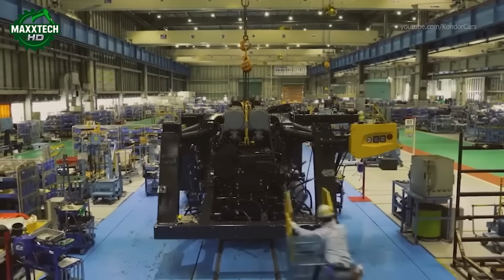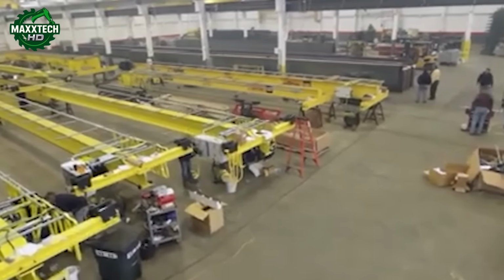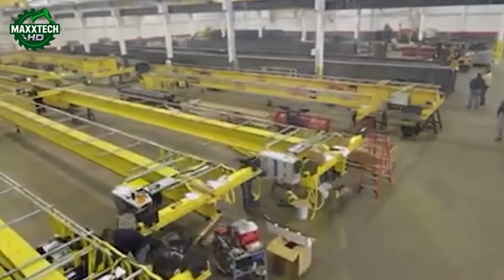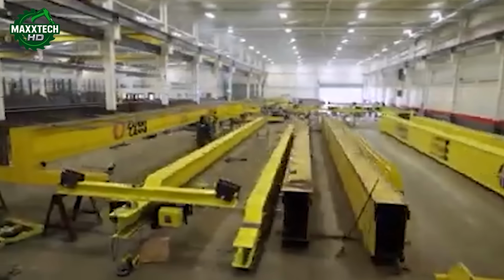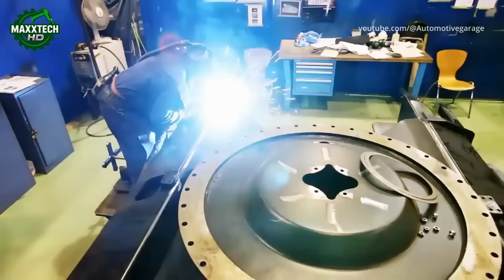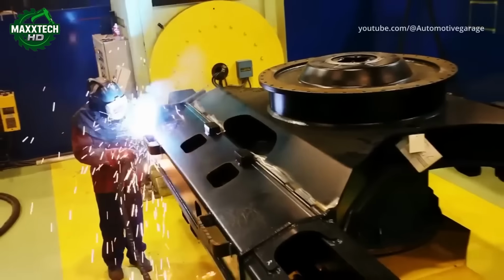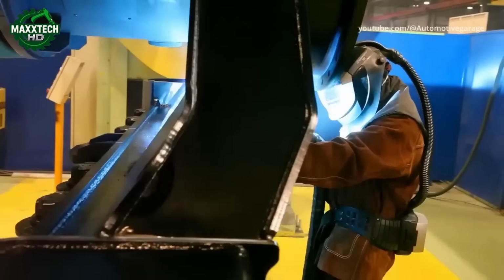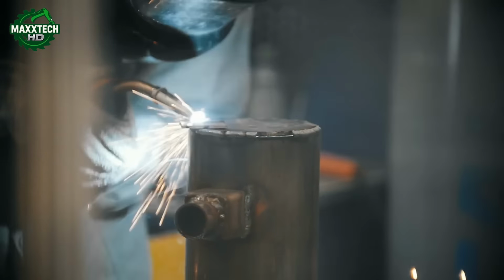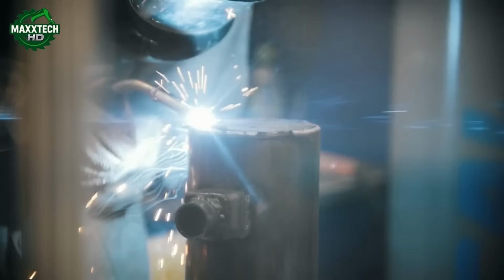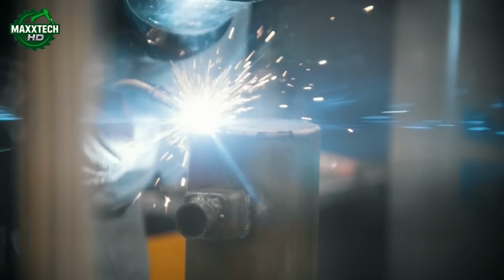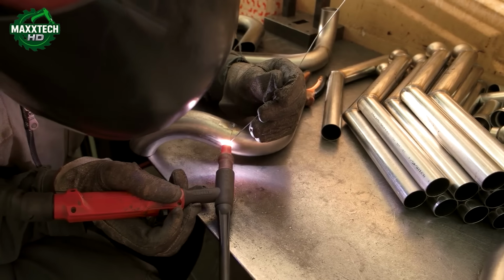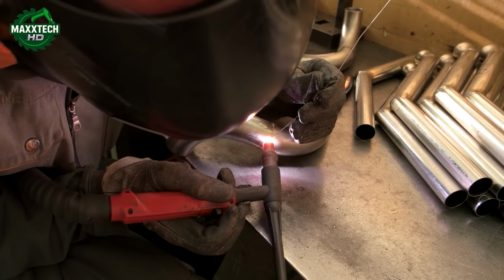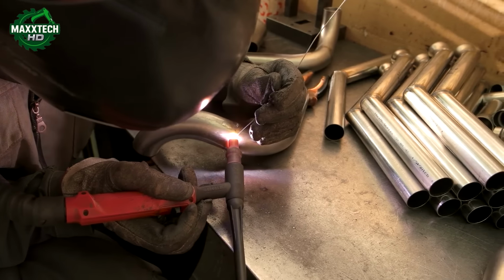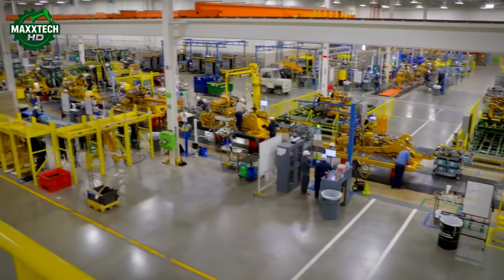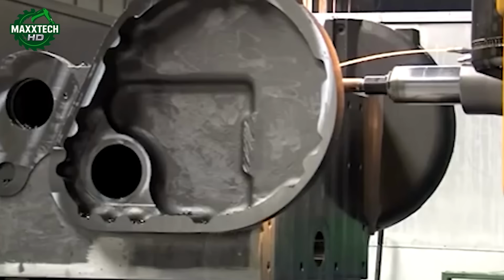These pieces are immense, ranging from over 440 pounds to more than 11,000 pounds each. Moving them is no small feat. They rely on a remote-controlled crane to lift and position each section. Once in place, the operator meticulously lines up the pieces, leaving only a tiny gap between seams. Bars are tightened and welding begins. Each section can take 3 to 4 hours depending on the complexity, and the team must complete an astonishing 18 welds in total. The frame gradually starts to take shape, but the real challenge is just beginning.